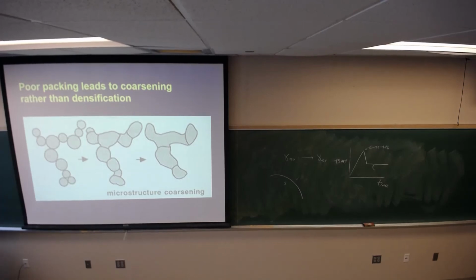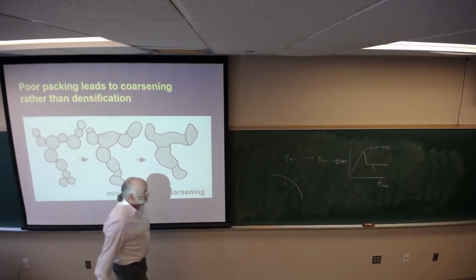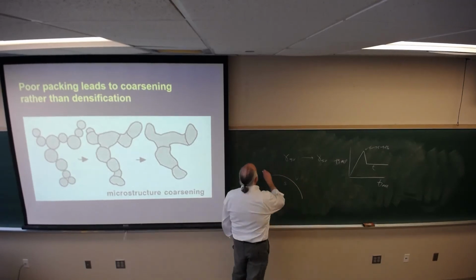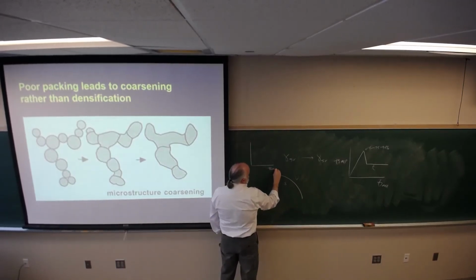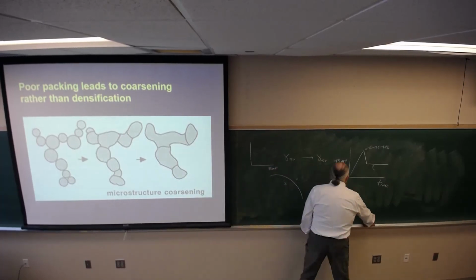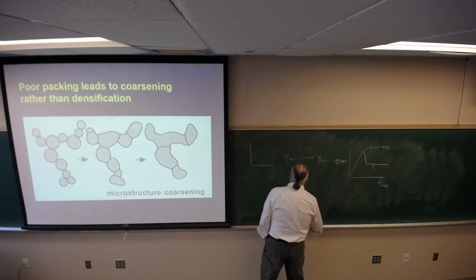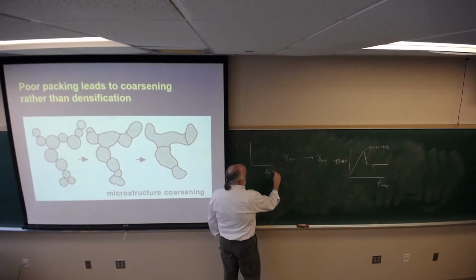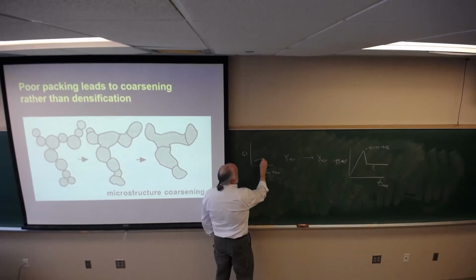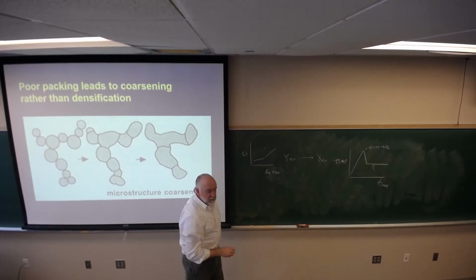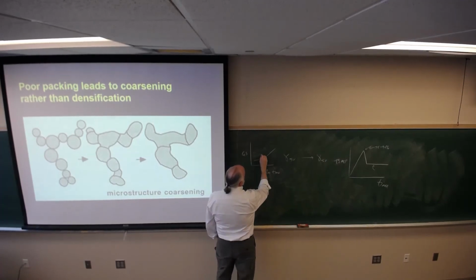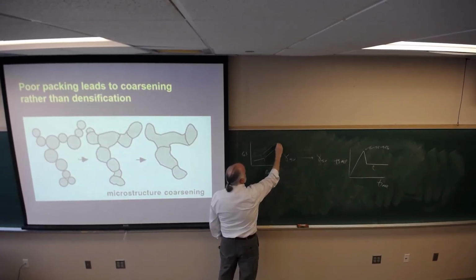And Sarah Whitke has been generating really marvelous data on the kinetics of grain growth associated with densification. And what she finds is that once, let's plot it this way, actually she does it versus log of time, which works also. She has two slopes like this. Not really a great big change. And she has other data. It shows if you do something like this. This might be 1500. This might be 1550.